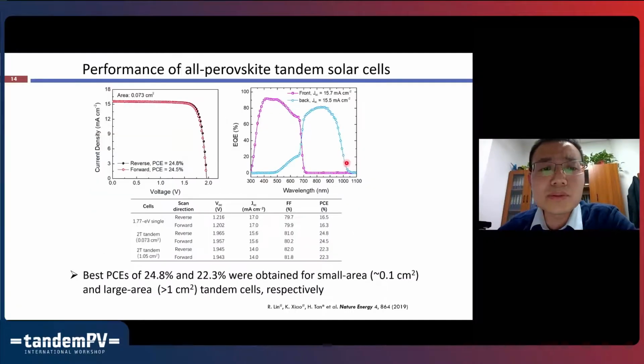And through this way, we further optimize the thickness of the two subcells so that we can get quite good current matching for the two subcells. So after the optimization, we can increase the efficiency of the all-perovskite tandem devices up to 24.8% from the JV measurement. We also make larger area tandem devices to see the uniformity of the two subcells. We surprisingly found that even when we increase the area up to 1 centimeter square, we can still see quite high VOC and fill factor values.